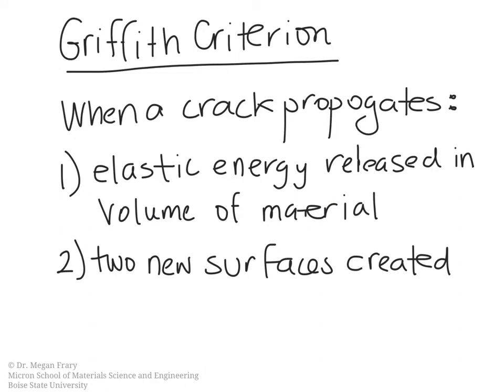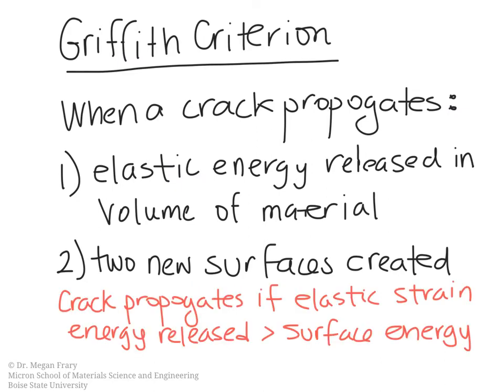The two energy terms are: first, when the crack propagates, elastic energy is released in a volume of material; but when that crack propagates, we also have two new surfaces being created. The crack will propagate in the case when the elastic strain energy released is greater than the surface energy it takes to create those two new surfaces.